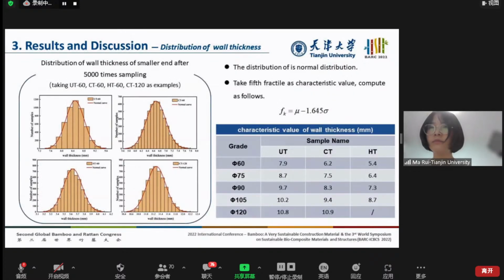The distribution of the wall thickness of the smaller end was obtained after 5,000 times sampling. Representative results are shown here. The fitting results show that the distribution of both thicknesses is normal distribution. The fifth percentile is regarded as the characteristic value and can be calculated according to this formula. The results are listed in this table.